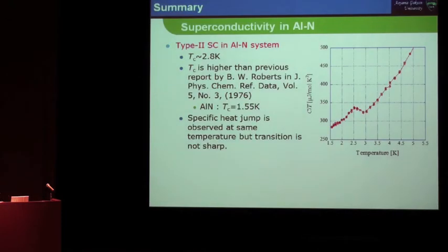So we would like to know the bulk nature of the superconductivity in aluminum nitride. We made a measurement of the heat capacity in the aluminum nitride, and it's not a sharp peak. However, we clearly observed the specific heat jump at this temperature.